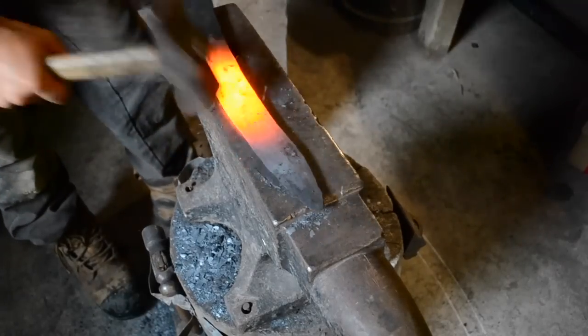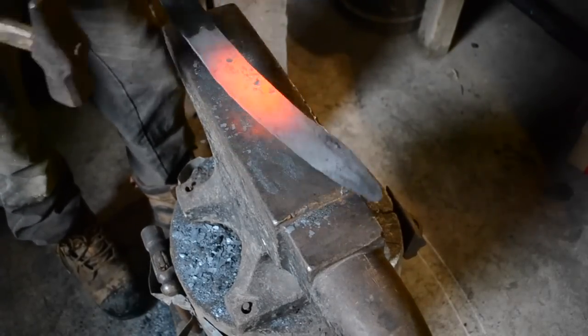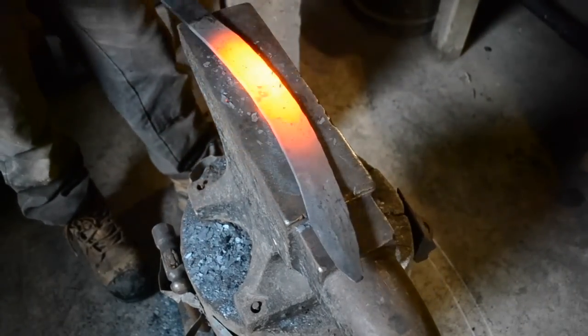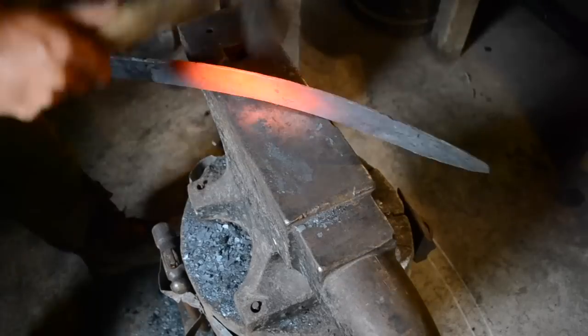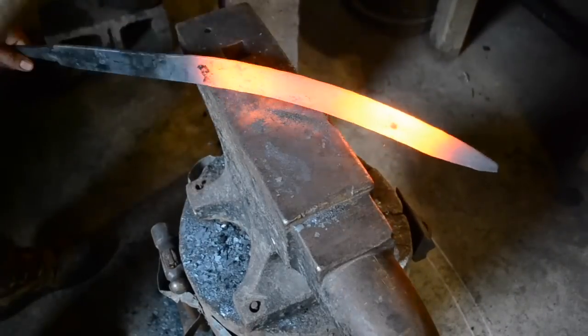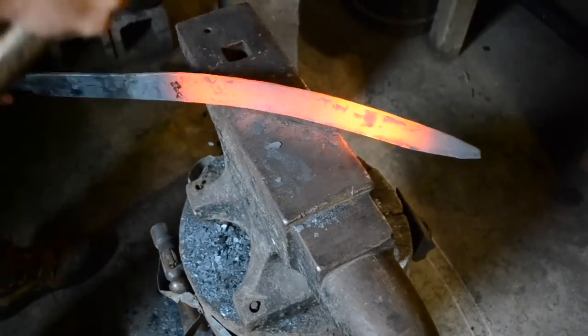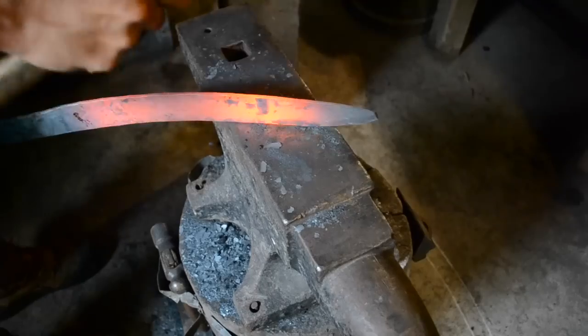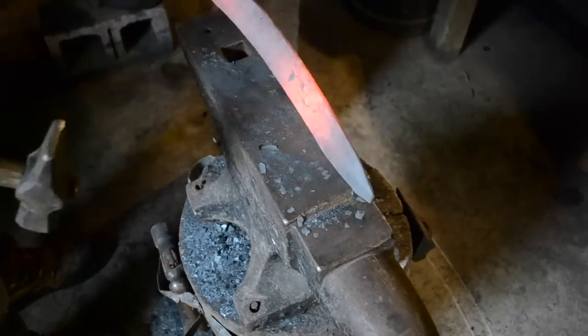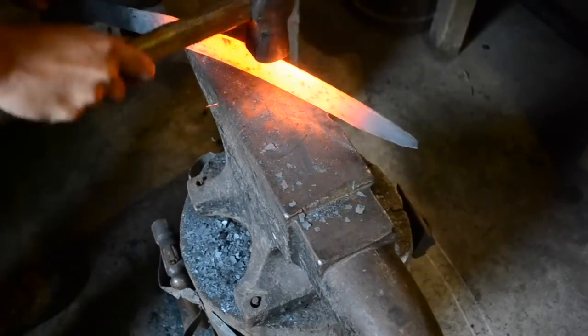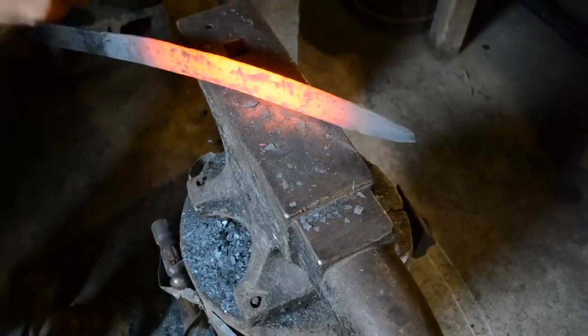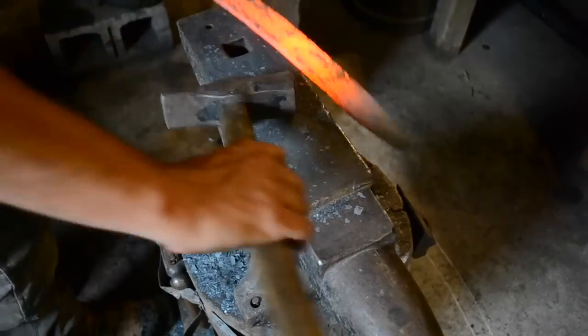Now back to the true edge. Every blow here is going to make the grinding a little bit easier. The blade is starting to take on a rather extreme degree of curvature, so I'm going to straighten this out. I do this by laying it diagonally across the anvil and then moving it back and forth as I tap it. You want to hit it very gently here so that you don't deform the edge. If it were thinner, I would be using a wooden hammer.